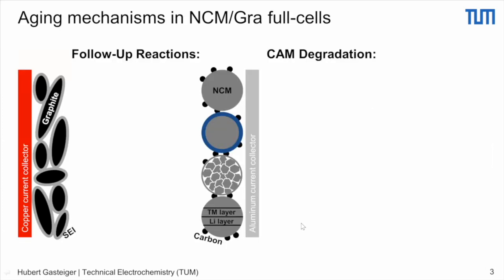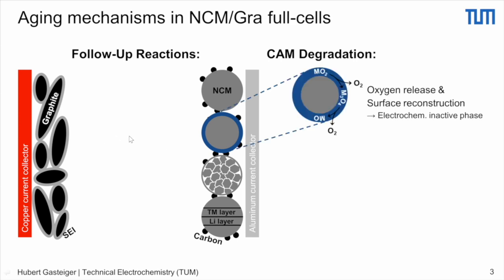And so if we look at the different aging mechanisms with respect to the cathode active materials, there's a few things which are pretty well known. And so when we look at an electrochemical cell, what we have is that particularly at higher potentials, the NCM materials release oxygen.